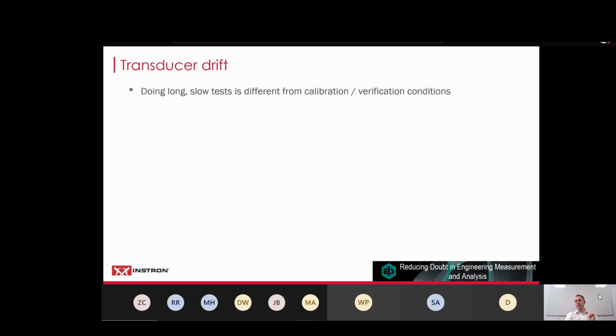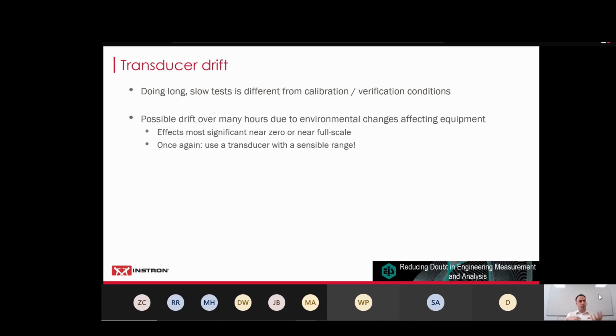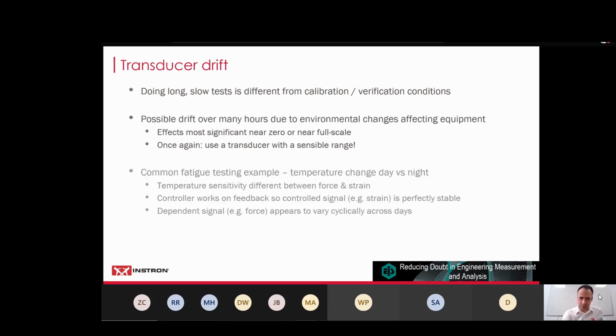And there are things that can creep in there where you can get drift happening in the transducer due to environmental changes, especially. Now, this is most significant where the temperature changes. And this is why, once again, mechanical testing laboratories should be reasonably temperature controlled, because a few degrees difference can be enough to shift the zero point on your measurement, or it can shift the overall full-scale reading. So once again, for the people at the back, use a transducer with a sensible range.